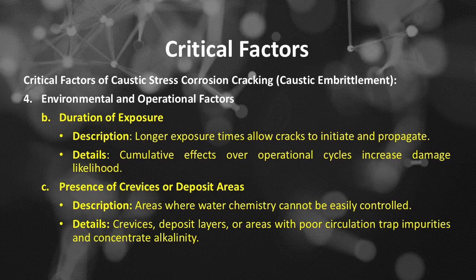Environmental and operational factors. Number B is duration of exposure. Longer exposure times allow cracks to initiate and propagate. Cumulative effects over operational cycles increase damage likelihood. Environmental and operational factors. Number C is presence of crevices or deposit areas, areas where water chemistry cannot be easily controlled. Crevices, deposit layers, or areas with poor circulation trap impurities and concentrate alkalinity.